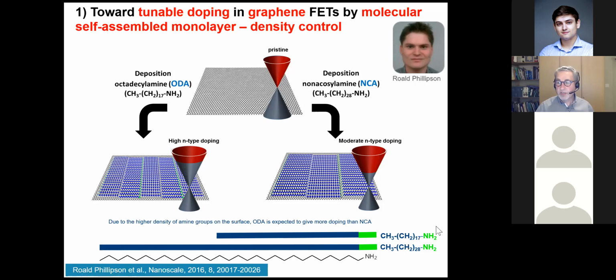Given that, for instance, an amine functionality can act as a doping unit to create N-doping on the surface, an obvious approach from our perspective to control the density of amino groups on the substrate is to have them organize on the substrate in the form of a self-assembled molecular network. So we took a short alkyl chain and a long alkyl chain amine and exposed that to the substrate. Now, this is what we hoped would form in terms of the molecular organization.